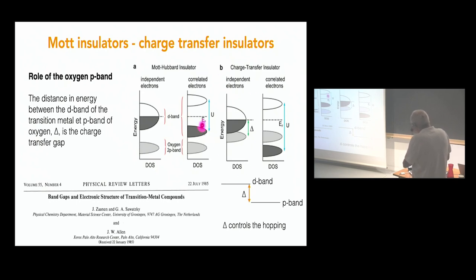But if the oxygen p band is very close to the d band, like in this case, and this is a case of the nickelates, when you open the gap, the relevant gap will be the charge transfer gap between this upper part of the d band and the oxygen p band. And this is discussed in this famous paper of Zaanen, Sawatzky and Allen.